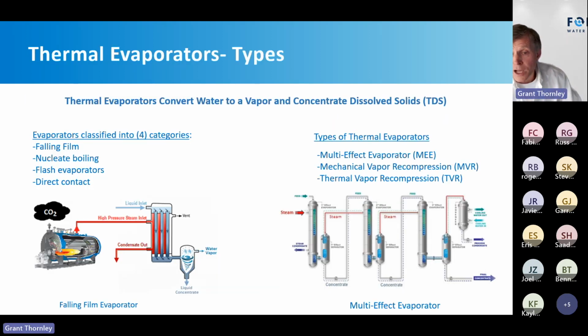It's a straightforward process, but there are lots of different types of configurations and operations of them. Most commonly, you're going to have a steam boiler firing up to put steam into where the calandria or vertical tubes are. And that's going to be the thermal energy required. Categories of thermal evaporators are falling film, nucleate boiling, flash evaporators, and direct contact. You can take a look at those a little bit more, but essentially it is heat transfer into the solution to cause the water to distill off.